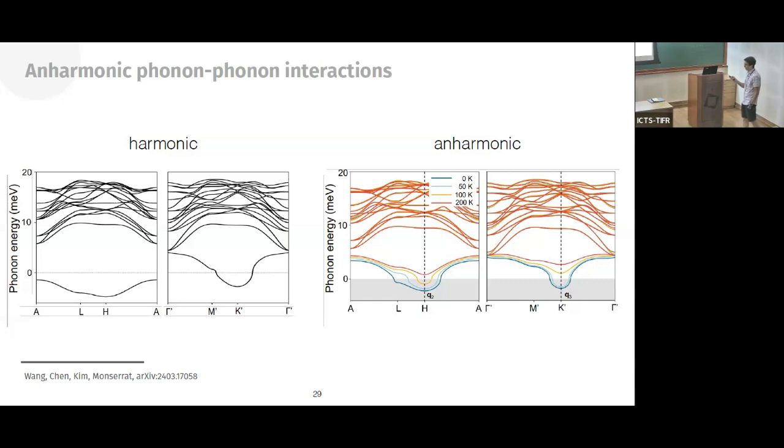So this seems to suggest that if you start from the high temperature phase, you first hit the Q2 instability, and then you hit the Q3 instability. I don't want to say that agrees with the experiment, but experimentally you do see first the development of short-range Q2 order, and then the Q3 order dominates and takes over. So that at least has the same ordering.